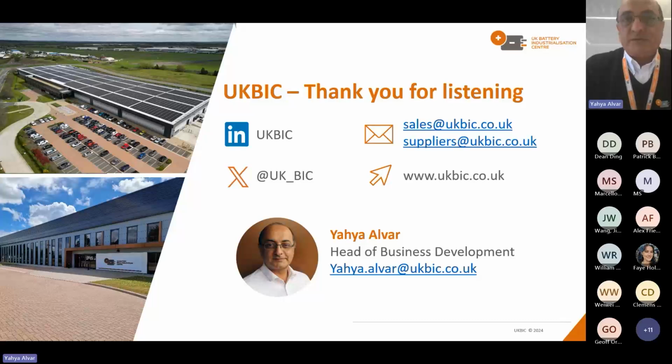In fact, we also had another NMC 811 customer on site with a different mixing recipe and different material from a different supplier. We mixed and we kept the slurry under agitation for about 4 days, and there was no problem at all, even after 4 days, in the slurry rheology. No gelling at all.